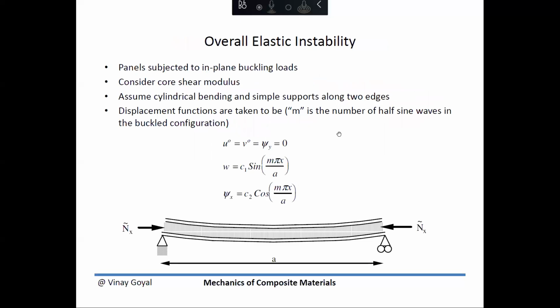You can also look at the overall elastic instability. That means I apply a load globally to a structure, and that causes a global instability of the structure. Here we assume that the in-plane deflections are zero, and that we only have an out-of-plane deflection, and that we may have some amount of shear deformation in this plane. And here, since we're not looking at the through-the-thickness direction, gamma_yz is set to zero. So we want to see what it takes to buckle a panel from the global perspective.